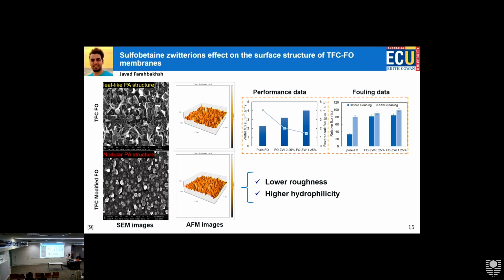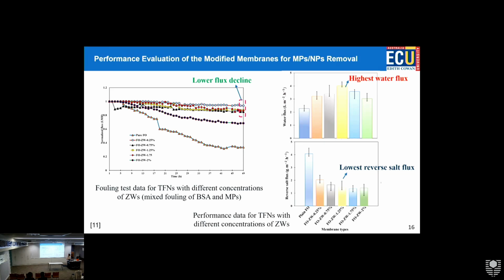The fouling data with microplastics showed that the pure membrane initially has less flux. As I mentioned, for FO membranes, we can recover a majority of the flux. But with the two modified membranes, both of them recovered, and the initial fluxes are higher compared to the original membranes. So, as I mentioned, we had lower roughness and higher hydrophilicity. Both of them combined are effective in enhancing the water production as well as fouling minimization. This was a mixed fouling of BSA and microplastics that was tested.